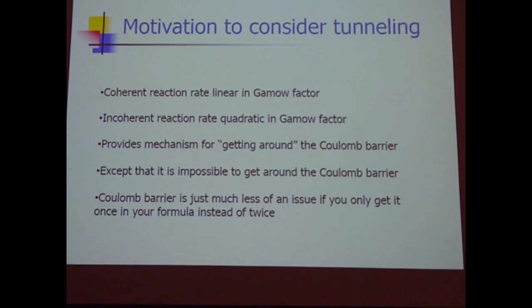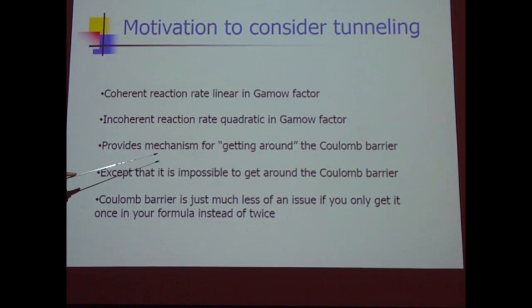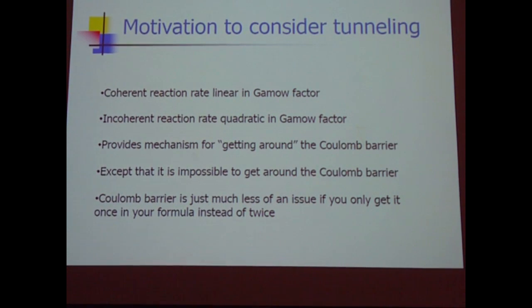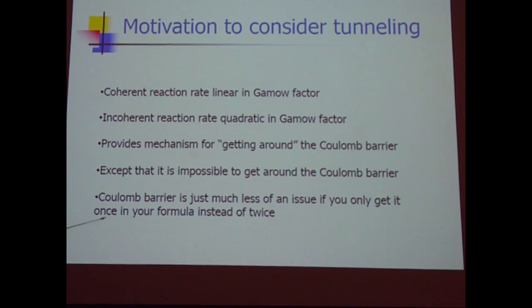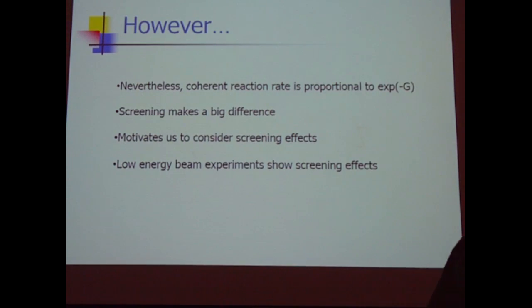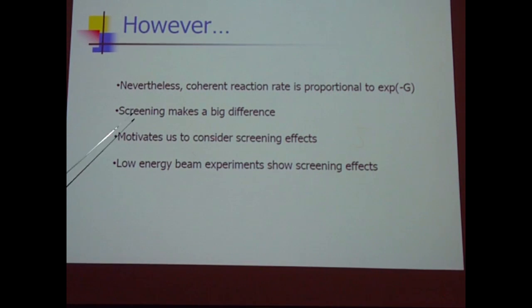Okay, let's talk about screening. Why are we interested in screening? We've seen that the coherent reaction rate is linear in the Gamow factor, and incoherent reaction rates are quadratic in the Gamow factor. Now the coherent business provides us a mechanism for, quote unquote, getting around the Coulomb barrier, except that you can't get around the Coulomb barrier. It's just less of an issue if it's only showing up once, but it's still there once. Because it's still there once, we have to worry about screening. So screening makes a huge difference even if you're only linear in the Gamow factor. That motivates us to consider screening effects, and that drives us to consider low energy beam experiments.